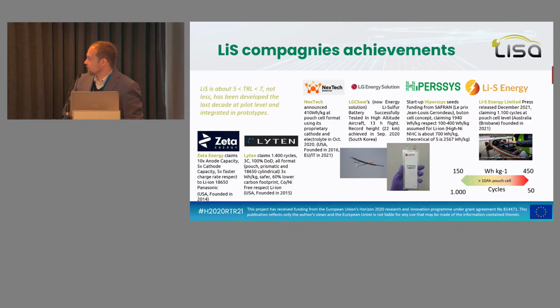And regarding the performance, you have a kind of threshold between energy and cyclability. So with high energy density, you get a low number of cycles, and with lower energy density, you can reach something that is comparable to lithium ion, for example.